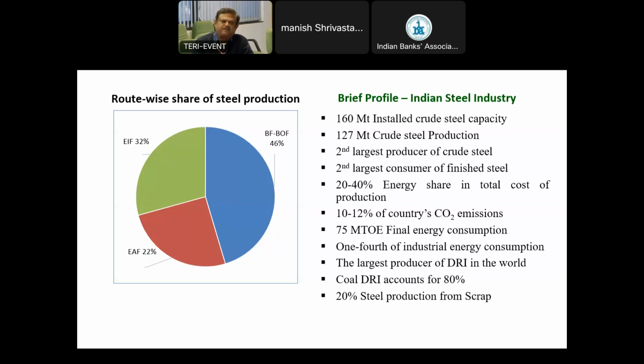So in the pie, you can see that the major chunk is coming from the large industries, which are blast furnace, basic oxygen furnace, BF-BOF, as we call it shortly, at about 50%. So 50% of the steel production comes from this route, which is predominantly in the hands of 5 to 6 large corporates like SAIL, Tata's, Jindal's, AMNS, ArcelorMittal, and JSPL.